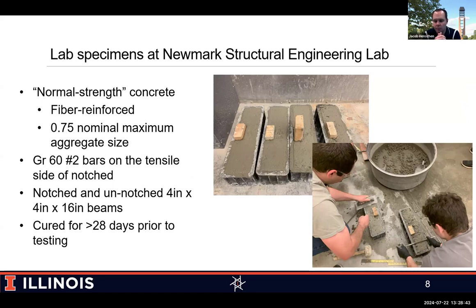And with concrete, we use what I've always called my typical concrete. It's a formulation with a 0.42 water cement ratio, so it gets us around 4,000 psi, using standard lab sands and 3/4 inch nominal maximum size limestone coarse aggregate, a very, very standard mixture. This is what Illinois DOT uses for a lot of their pavements and things like that. The only thing we pulled out of it was the air entrainment.